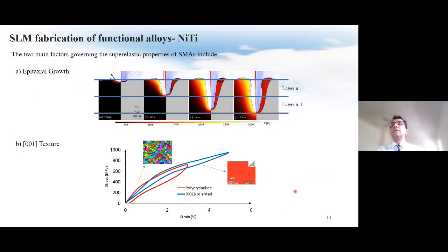The next step was to further narrow down the parameters in a way to ensure the as-fabricated part demonstrates superelasticity. It is well known that superelasticity can be achieved through modification in the microstructure and texture of the fabricated part. In regard to the microstructure, it has to provide epitaxial growth, I mean an appropriate level of remelting between each layer. As you can see here, if the energy is not enough for the fabrication, the layer would not be connected to the previous layer. On the other hand, if the energy is excessive, there would be overheating, which intensifies residual stresses and causes significant grain growth, which are undesirable in general.